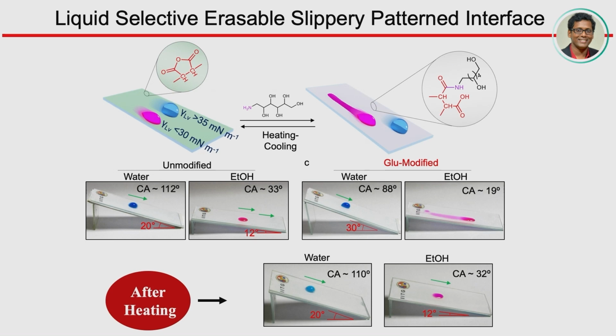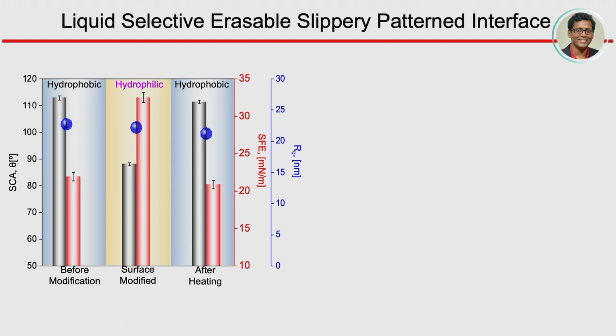So what is going on here? If you see, when we started with this particular coating before the modification, it remained hydrophobic. The roughness remained somewhere around 22, 23. Then you go for the hydrophilic modification, you are not playing with anything on the roughness factors, right? So the topography remains very similar, roughness remains very similar. What's happening is the interface becomes hydrophilic in nature. The water contact angle dropped from 110 or around that to something below 90. And the surface free energy is elevated now above 30, around from 22 to 30 now. And then when you are heating and cooling, at that point you can see it again becomes hydrophobic, and the roughness remains very similar, it's just the surface free energy again dropped, right.